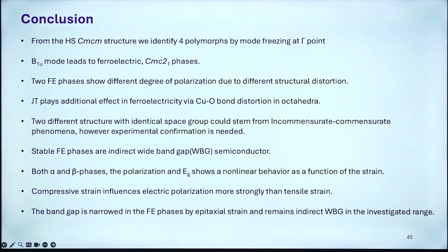So finally I would like to conclude, I am close to 5:30. From the high symmetry Cmcm structure we identify 4 polymorphs by mode freezing of the 4 modes, and the B1U mode leads to the ferroelectric Cmc2₁ phase. This is a problem for the experimentalists, because one has to do infrared, because this is not Raman. Here we could conclude that this B1U mode is the key player for driving that particular material.